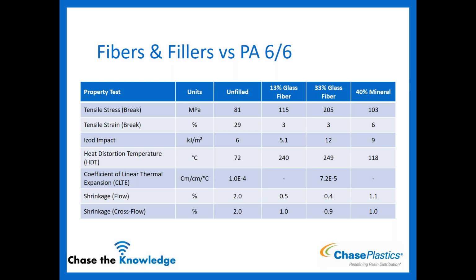So we talked about it improving the mechanical. So if you look at your tensile stress, you start at 81 and an unfilled, and you get all the way up to 205 if you're using 33 glass. Now, if you follow the pattern, 13 is an improvement, 33 is an improvement. If you add even more, it's going to be an improvement as well. So if you went up to a 50 glass or a 60 glass, again, continue to improve. And then the mineral, you can see it did improve it a little bit as well, but like we've mentioned, not as drastic as it would be as the glass.